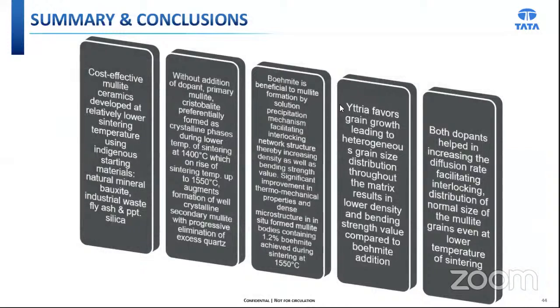So cost-effective mullite ceramic has been produced from the indigenously available raw materials and industrial waste fly ash. Without addition of any dopant, primary mullite is produced and the cristobalite is preferentially formed, but with rise in temperature, the cristobalite disappears and the mullite formation accelerates with rise in the secondary mullites.